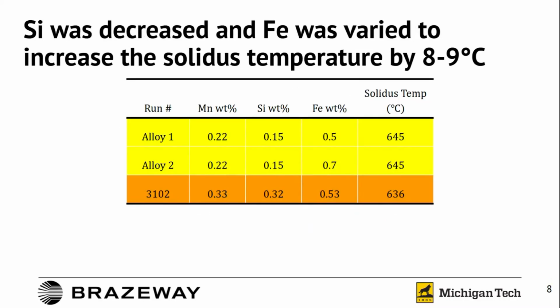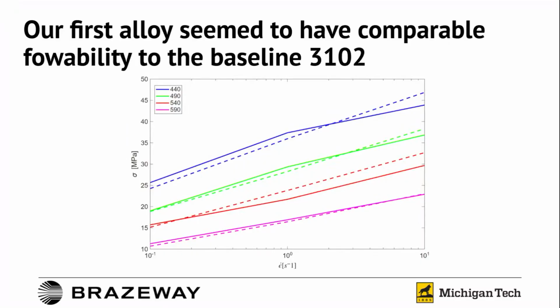Also, in our alloy design, we decided to decrease the manganese content and silicon content, as well as varying iron. That provided an 8 to 9 degrees Celsius increase in our solidus temperature. We also did some more Gleeble testing and flow stress testing on our first and second alloys. And based on this graph, we can see that the flowability is pretty comparable to the baseline 3102 at high temperatures. However, as the temperature decreases, that flowability does decrease.